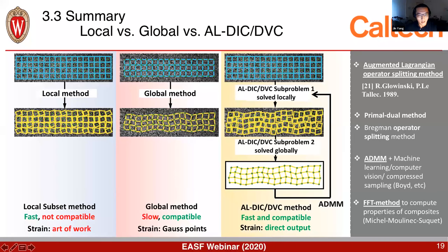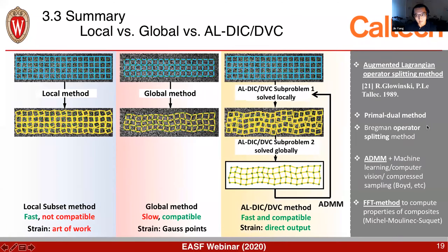Quick summary: the local method solves all subsets independently — it's fast but solutions may not be compatible, and computing strain requires additional filtering and differentiation. The global method guarantees kinematic compatibility but is more expensive. For ALDIC, the problem is decomposed into two sub-problems: sub-problem 1 uses the local solver (fast, parallel), and sub-problem 2 is a global solver but contains no image grayscale values, so it's also fast. The ADMM converges in three to six steps, the strain tensor F is a direct output, and this method is useful not only for DIC but also relates to machine learning, computer vision, and materials science.